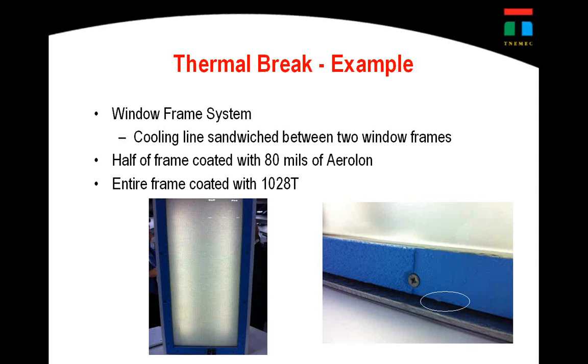So what you're looking at on the right side is the aluminum window frame that is now sweating because it's a cold temperature that's looped in there. I think the temperature of that is 42, 47 degrees, something like that. And now we have the ambient temperature outside in the room that's 75 degrees F or whatever. And you're seeing the sweating occur. The half side that you see past that screw head is now coated with basically 80 mils of Aerolon. And we have no condensation that has occurred.